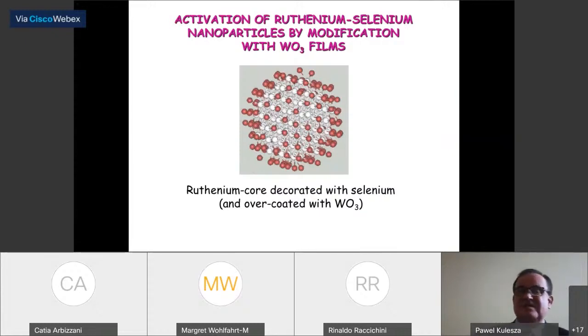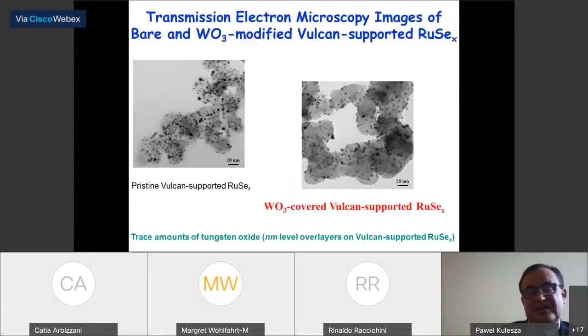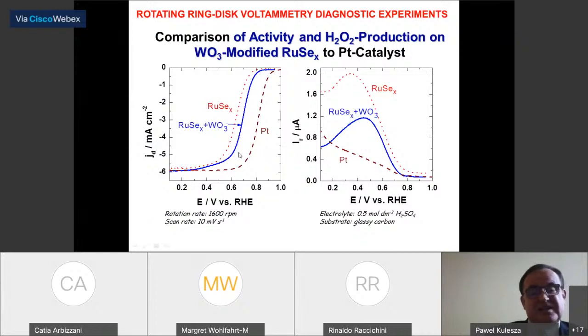So ruthenium selenium systems, ruthenium modified on the surface with selenium, is like cheating in a sense, because we make ruthenium much more metallic as a corrosion protection. So at that time, we also worked on ruthenium selenium. We had samples from different sources, from the United States, from Germany, and from Italy. And we modified them with tungsten oxide. We believed that it was a little bit more stable than polyoxometalate on the surface. And indeed there was a shift in the reduction potential for the oxygen reduction. And the amount of hydrogen peroxide decreased. The system was never as great as platinum, even not optimized platinum, but the ruthenium selenium was not optimized either, but the results were quite interesting.